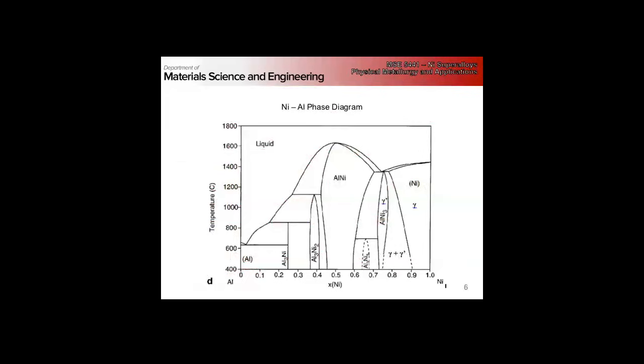Now if we look at the other side, the aluminum nickel side, there's no appreciable solubility of nickel in aluminum. It's basically line compounds, pure nickel or pure aluminum and the intermetallic. Whereas on the other side we have roughly 25% solubility of aluminum in nickel.